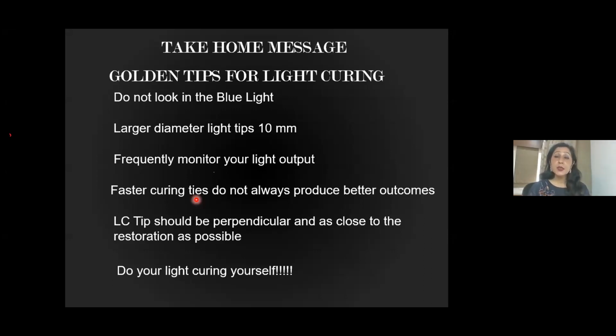Larger diameter tips should be taken and they should be around 10 millimeters, because some manufacturers give small tips which are not good because they don't cover the whole surface. So you will have to place the light cure probe on all the surfaces incrementally, and that takes a lot of time. So if you have large diameter light cure tips around 10 millimeters, that would be best, so that you can cure continuously.